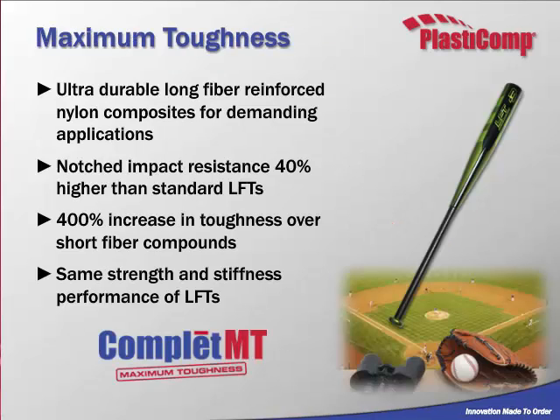Now another product that we've had some very good success with is the maximum toughness grade. And I think I mentioned earlier that in thin-walled applications, this is where this product really shines. You can get a notched impact increase that's 40% higher than our standard LFT products, and 400% increase over some of the short fiber compounds. So again, when impact strength is of the utmost importance, this would be the material to choose.